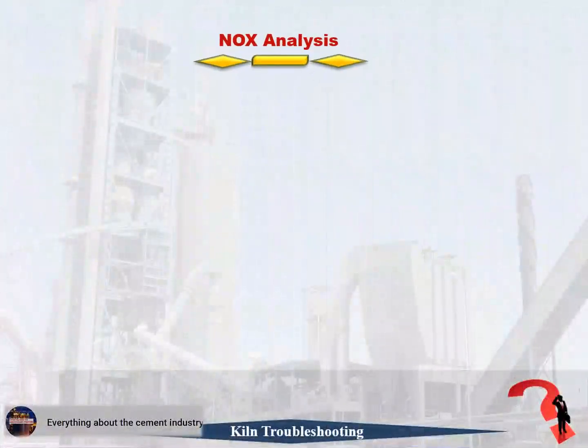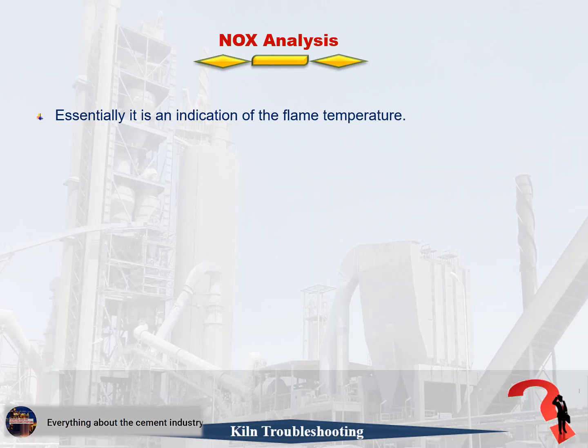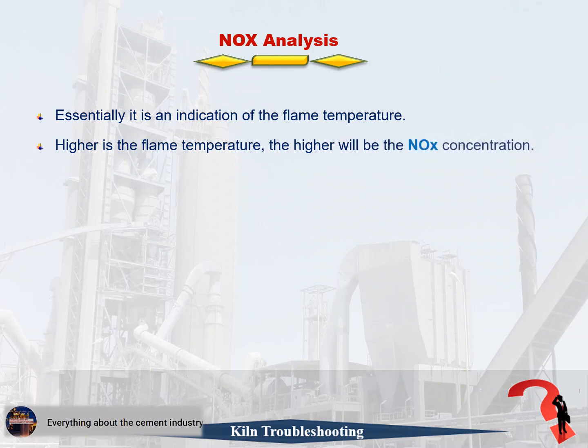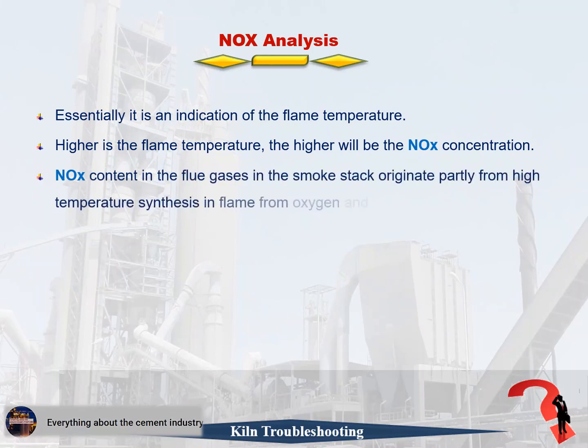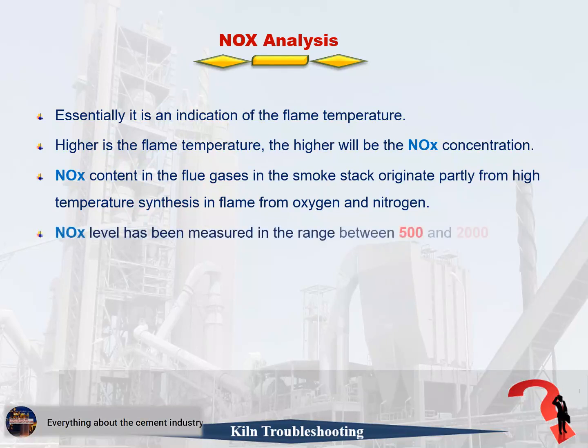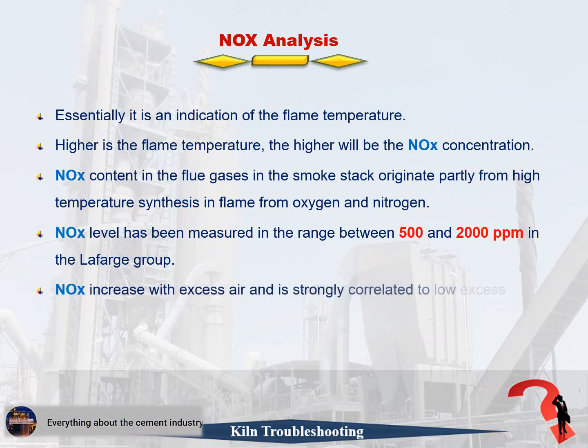NOx analysis. Firstly, essentially it is an indication of the flame temperature. Secondly, higher is the flame temperature, the higher will be the NOx concentration. Thirdly, NOx content in the flue gases in the smokestack originate partly from high temperature synthesis in flame from oxygen and nitrogen. Fourthly, NOx level has been measured in the range between 500 and 2000 ppm in the Lafarge group. Fifth, NOx increase with excess air and is strongly correlated to low excess air levels.